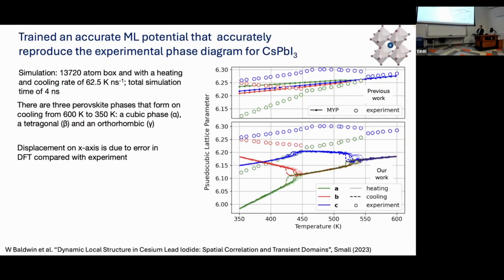We started this work a few years ago. We had a paper out from Will Baldwin, who was a student in the group of a collaborator of mine, Gabor Csányi, at Cambridge. So this is his work from two summers ago now. We started by trying to map the phase diagrams using a machine learning potential, a graph neural network specifically. What I'm showing you here, in the top panel, is the previous work in this field. This is a parameterized, classic force field. And you can see that there's not much change in the lattice parameters themselves over the temperature, compared to the experimental one here.